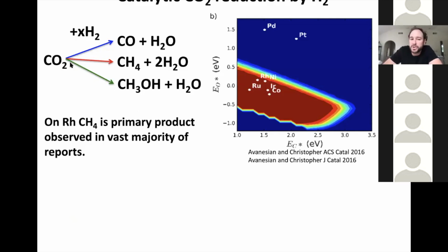So if you do a simple 2-electron reduction, you can go to CO. The complete reduction sends you all the way to methane, and you can do some partial reduction to methanol, and all of these have various potential applications. Our interest was in rhodium catalysts, where it's known from a lot of different analyses that rhodium falls in the regime where you get primarily CH4 selectivity in this reaction. So on rhodium catalysts, there's maybe 100 or 1,000 papers in literature that show if you take CO2 and hydrogen, you react them on rhodium surfaces, you make mostly methane.